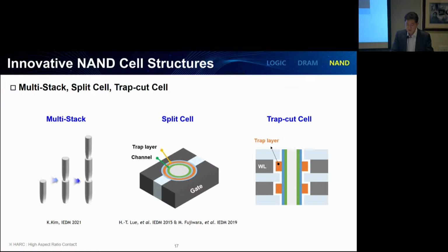So first, let's have a look from a structural point of view. As we stack more and more layers, high aspect ratio contact etch to form a channel hole becomes extremely challenging because the vertical pitch of a single layer is no longer scalable, therefore requiring innovative cell structures. And there are 3 promising candidate structures: a multi-stack, a split cell, and a trap-cut cell structure.